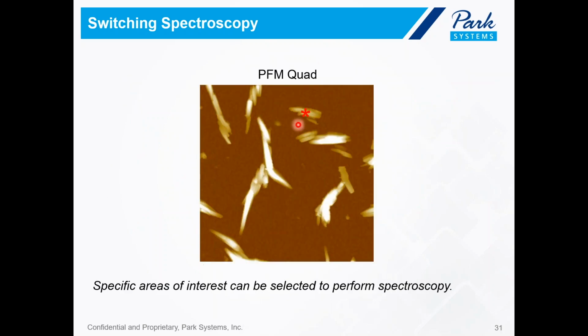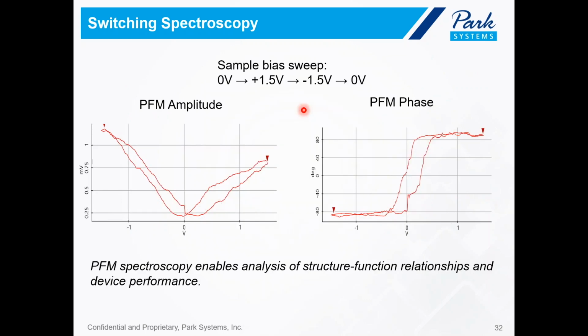So here is an example of switching spectroscopy. The red star here shows the location where the switching spectroscopy was performed. And here are the results of the switching spectroscopy. So we swept the bias from 0 to positive 1.5 volt, and then from positive 1.5 volt back to negative 1.5 volt, and finally back to 0 volt again.